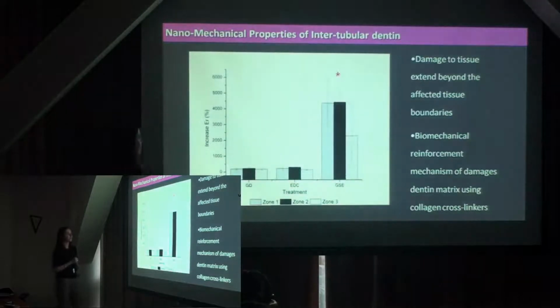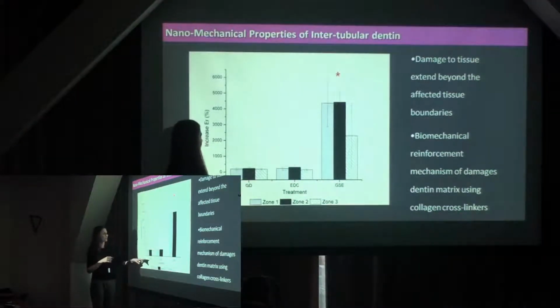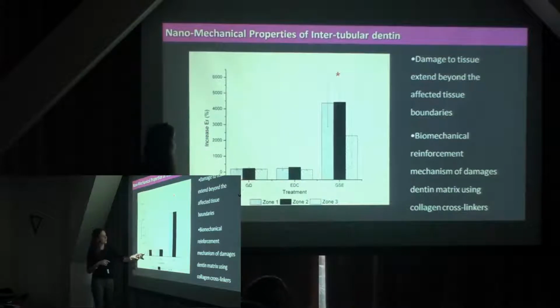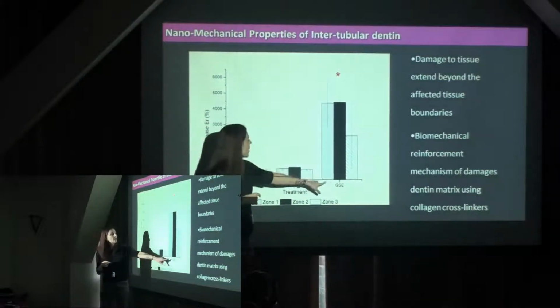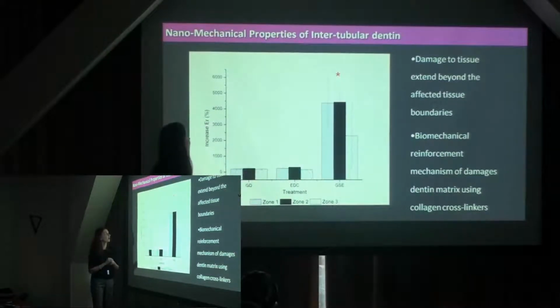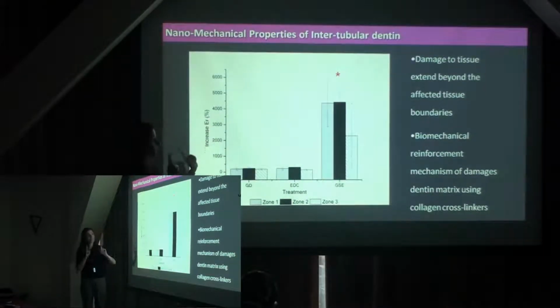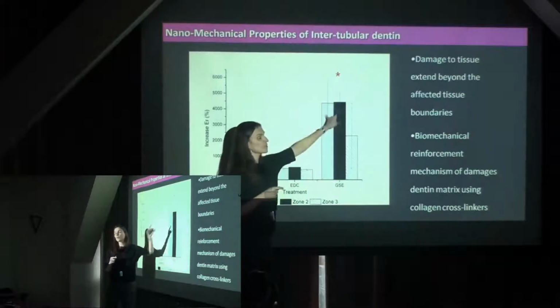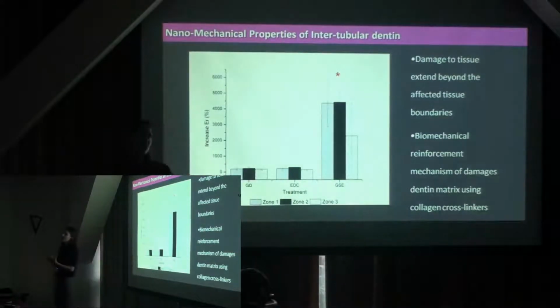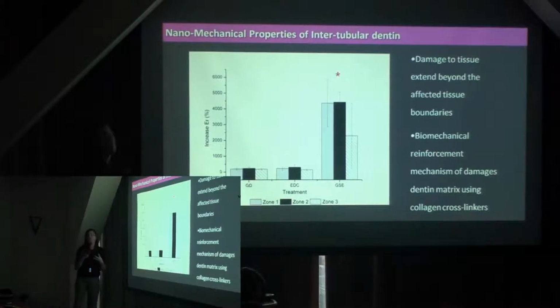And to just summarize what we've seen, this is a percentage increase in the reduced modulus of elasticity of about, I think, 200 to 250 times for glutaraldehyde and EDC, where we get for grapeseed extract about 5 up to 4,000 times. But what was interesting is that it reinforced more significantly where the decay process was taking place. So it reinforced that already damaged surface. And this for us is very valuable because that's where we're going to be using it more.